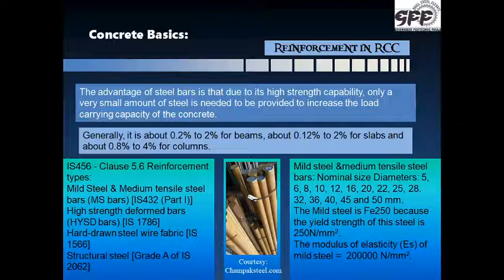Now IS 432 also states that bars of diameters up to 20 mm of mild steel grade 1 have minimum ultimate tensile strength of 410 Newton per mm square and minimum yield stress of 250 Newton per mm square. Please note, this is the ultimate strength, and the minimum yield stress is 250 Newton per mm square. I will be stressing on the yield stress again. Yield stress is 250 Newton per mm square with minimum elongation of 23%.